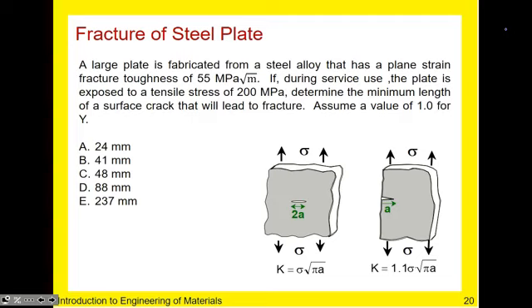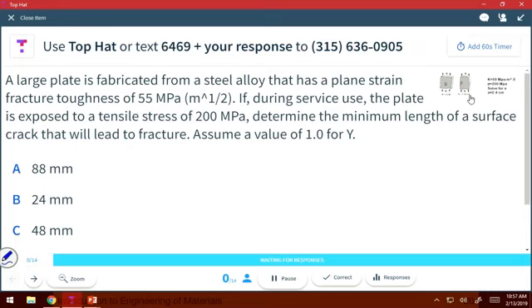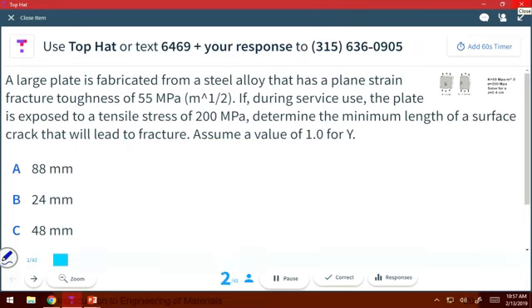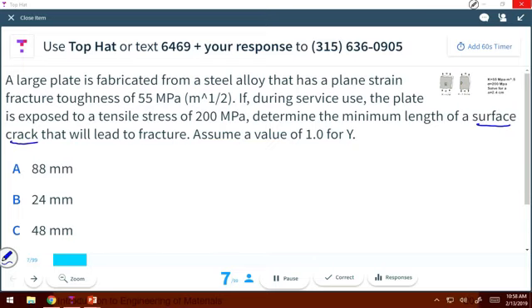Okay, so let's do an example, where, let me get this on Top Hat. So if you have a large plate that's a steel alloy, and it has a plane strain fracture toughness, so this is your K1C. And your book goes into nuanced details about what a plane strain fracture toughness is, but it has to do with the dimension of the material. If during service the plate is exposed to a tensile stress, that's your applied stress of 200 megapascal, determine the minimum length of a surface crack that will lead to fracture. So note this is a surface crack, okay? And assume that Y is 1.